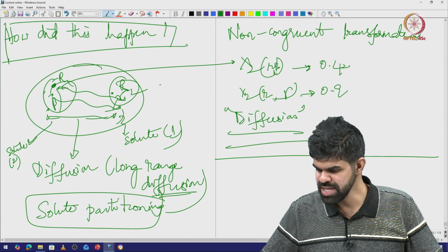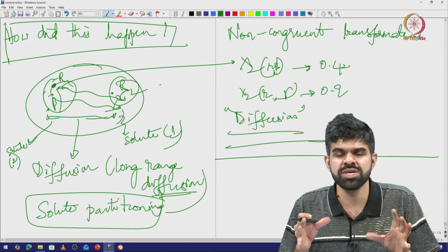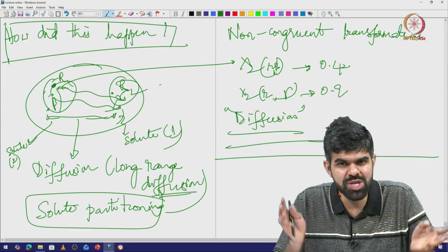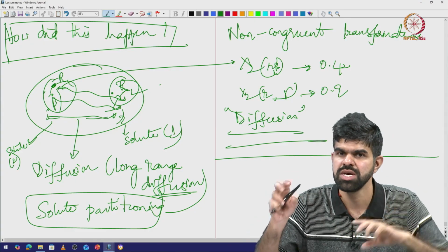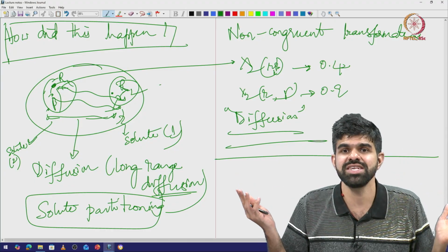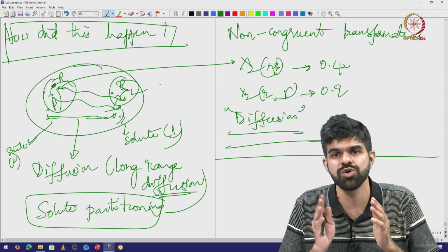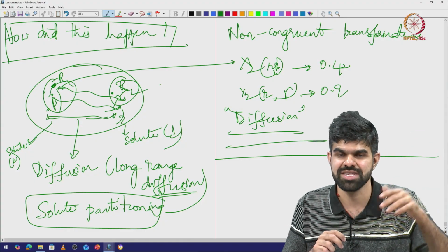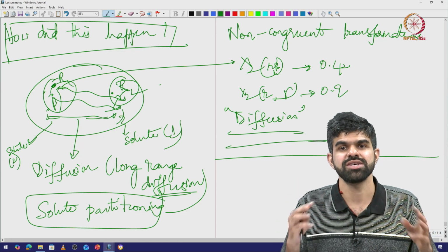Now, let us define certain things. So, now I understand what this phase transition is, what is meant by alpha giving rise to beta plus gamma inside a homogeneous material. So, some chunk is 2 rich, some chunk is 1 rich, and since it is 2 rich, it cannot crystallize in an alpha phase, it has to go to some other phase now. That is what thermodynamics is saying at that volume and at that temperature and pressure, and so it goes to what is called a beta phase. Okay. So, when it is 1 rich, it has to go to some other phase. So, that turns out to be a gamma phase.